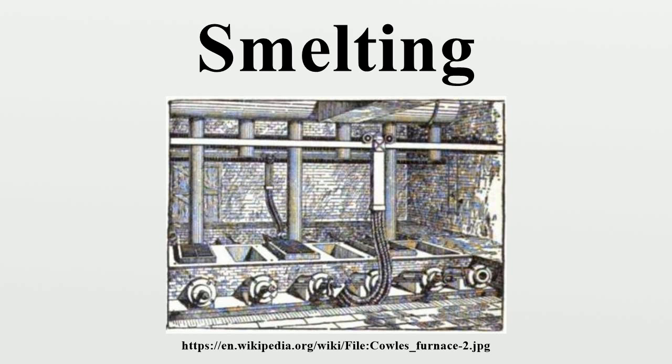Traditionally these were used for carrying out the first step, formation of two liquids, one an oxide slag containing most of the impurity elements, and the other a sulfide matte containing the valuable metal sulfide and some impurities. Such reverb furnaces are today about 40 meters long, 3 meters high and 10 meters wide. Fuel is burned at one end and the heat melts the dry sulfide concentrates, which are fed through openings in the roof of the furnace.